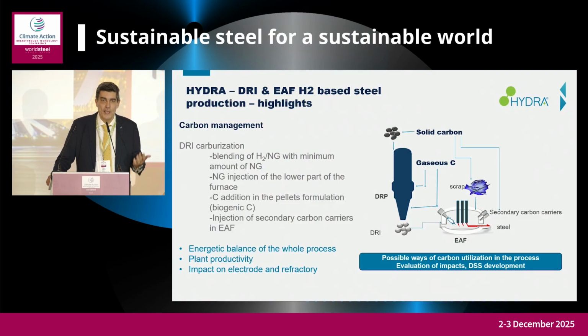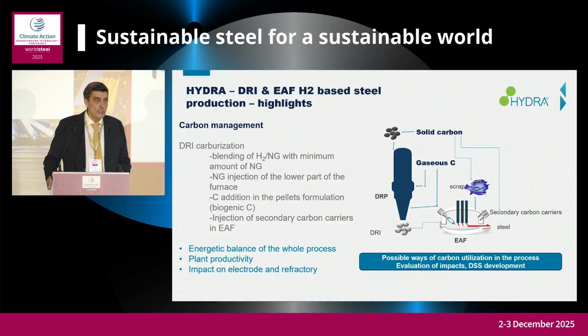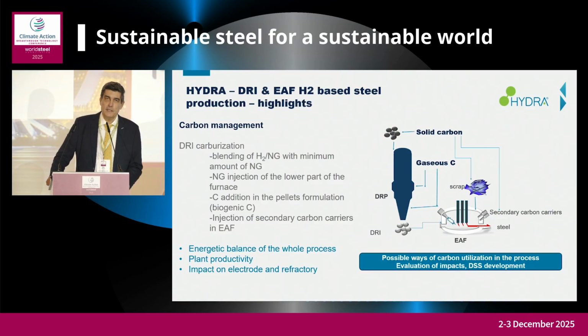So the carburization of DRI, or the way in which we may face it, is an important matter. Basically, we can provide carbon to the process in different manners: as solid carbon in the mix of pellets, or injected into the electrical furnace, or as a gaseous carbon blended with hydrogen or injected in the lower part of the furnace. Which is the best optimization practice, or the best option? I would say it depends on the steel that we are going to produce, but in any case, more insights can be obtained by performing a tailored experimental campaign.